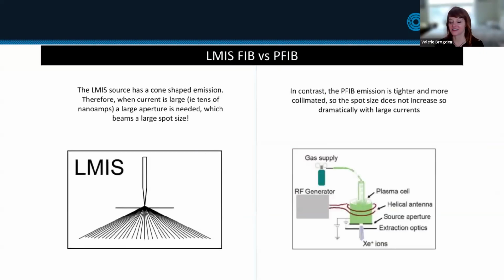Okay, yeah. So the first part of answering this question is understanding the difference in the shapes between the two beams. When you're using an LMIS source, a liquid metal ion source, usually with gallium, you have a cone-shaped emission. So you can choose bigger and bigger apertures that results in bigger and bigger currents, but the size of your beam is going to increase exponentially with the size of your beam current. PFIB, on the other hand, has a much more collimated beam. The emission is tighter and more collimated. So the spot size does not increase so dramatically with large currents.